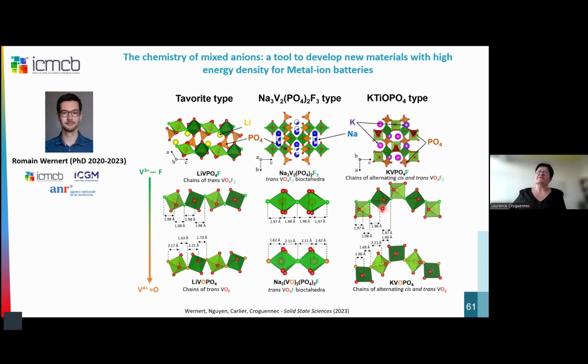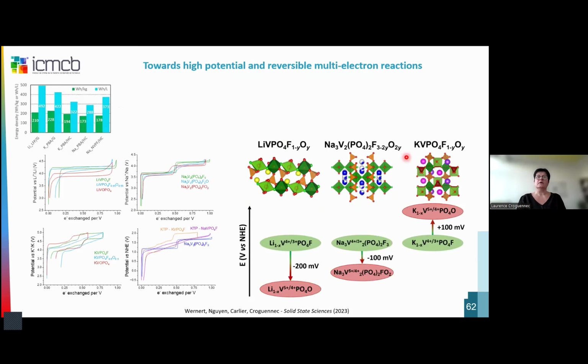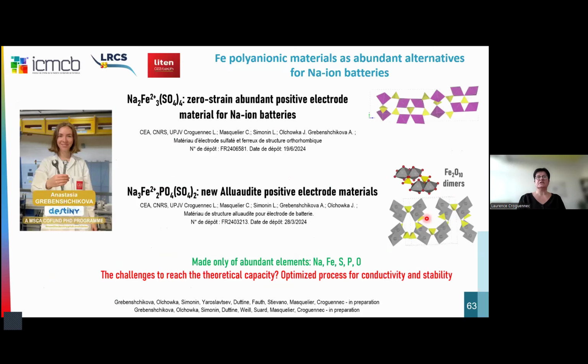Very recently, we have studied all these mixed anion chemistries with phosphates, tavorite structures, as you can see here for lithium, NVPF structure for sodium, and KTP-type structure for potassium-ion batteries. So this chemistry, not only the cation chemistry but also the anion chemistry, is really a source of new materials for batteries, because depending on the composition in anion, you can really play on the voltage and on the electrochemical curve, I would say the signature, and you can play on the potential of your batteries, here lithium, sodium, or potassium.